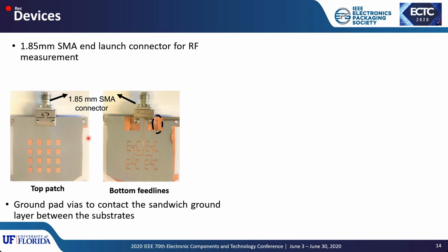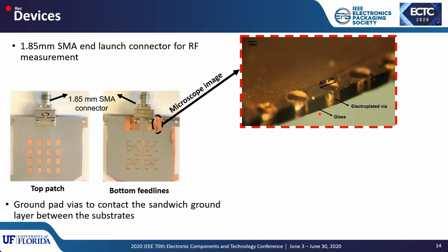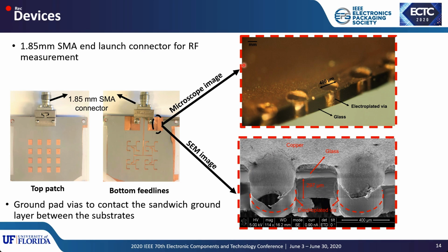As you can see, we used a 1.85 millimeter SMA connector in order to measure the performance of these devices. If you look closely into the vias on the ground plane, you can clearly see a very good uniform conformal coating of the vias. It is to be noted that the diameter of the vias for the ground contacts is close to 400 micron, whereas the vias on the feeding lines are close to 200 micron. The SEM image of the above structure is also shown here, and you can clearly see the deposited copper in the vias, and the thickness of the glass is close to the thickness used in the simulations, which is close to 300 micron.